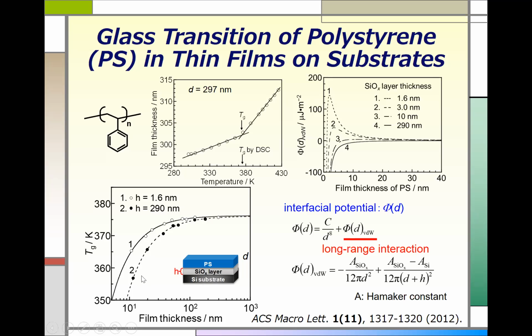But the point here is that we have a different parameter, h, and see here, h is the thickness of this oxide layer. If this h is changed, then the thickness dependence of the glass transition temperature is changed as well. So what this means is that this solid interface is also very important to understand the physical properties of this kind of polymer thin film. That's what I'm talking about.